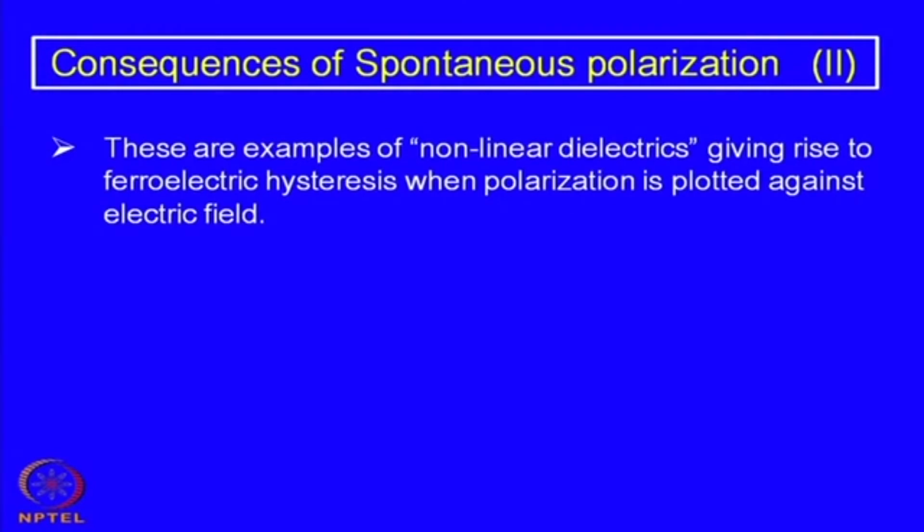We have earlier discussed linear dielectrics, where polarization is directly proportional to the electric field. But ferroelectric materials are examples of nonlinear dielectrics, giving rise to ferroelectric hysteresis when polarization is plotted against electric field.